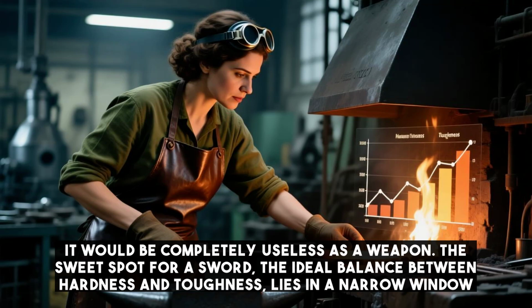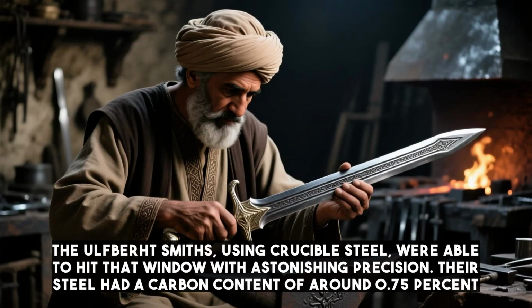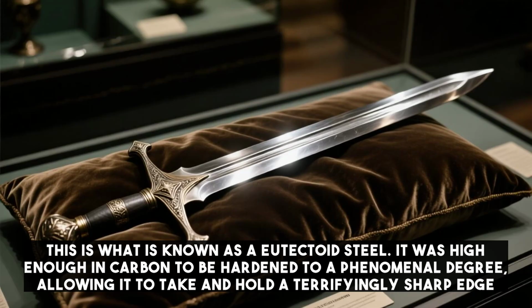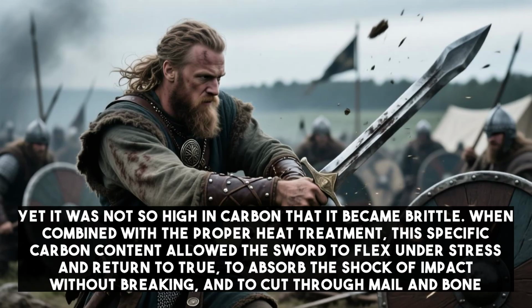The sweet spot for a sword, the ideal balance between hardness and toughness, lies in a narrow window. The Ulfberht smiths, using crucible steel, were able to hit that window with astonishing precision. Their steel had a carbon content of around 0.75%. This is what is known as a eutectoid steel. It was high enough in carbon to be hardened to a phenomenal degree, allowing it to take and hold a terrifyingly sharp edge. Yet it was not so high in carbon that it became brittle. When combined with the proper heat treatment, this specific carbon content allowed the sword to flex under stress and return, to absorb the shock of impact without breaking, and to cut through mail and bone.